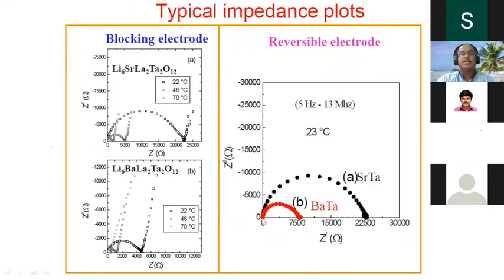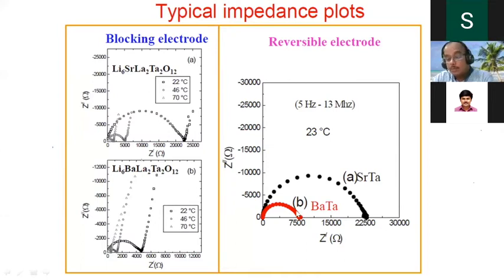Leave it. As far as my knowledge is concerned, this is the first material where we put metallic lithium on both sides as a reversible electrode, and the impedance pattern was measured with the barium. You couldn't find the tail, which tells you it's a good lithium ion conductor. The same thing with gold as blocking electrodes: you can see the tail, and I couldn't see any tail here. So the barium doped system is the best system. It can be electrochemically stable.